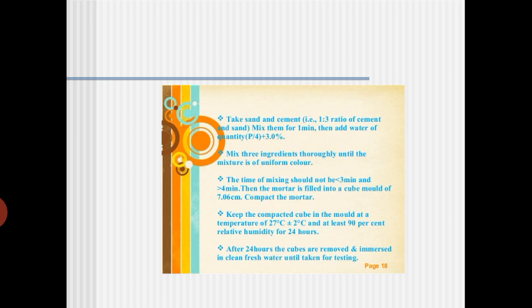Take sand and cement in a 1:3 ratio of cement to sand. Mix them for 1 minute, then add the water quantity, about 3%. Mix the three ingredients thoroughly until the mixture is of uniform color. The time of mixing should not be less than 3 minutes and not more than 4 minutes. This is very important: 3 to 4 minutes should be provided.